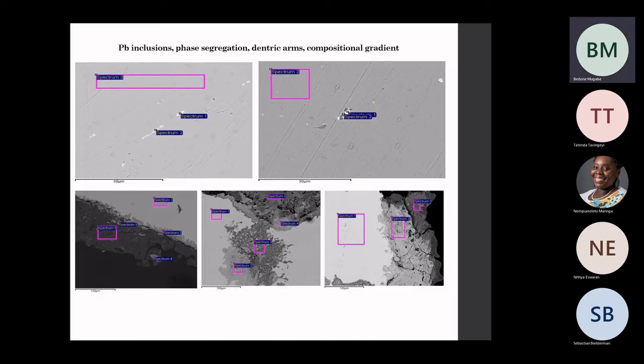Yes. So what we see here is just an example of the BSE images, or the photomicrographs that we have. So this is just to show you, from those polished blocks, if you examine them under OM and then you zoom in, if you examine them under SEM, you zoom in to the core of the samples. This is what the core of the metals were looking like. So on each and every photomicrograph, we managed to take probably more than three spectrums. So we're zooming within more than three areas at the core of the sample. So this is just a single sample. This is just two different samples to show you how diverse they were.